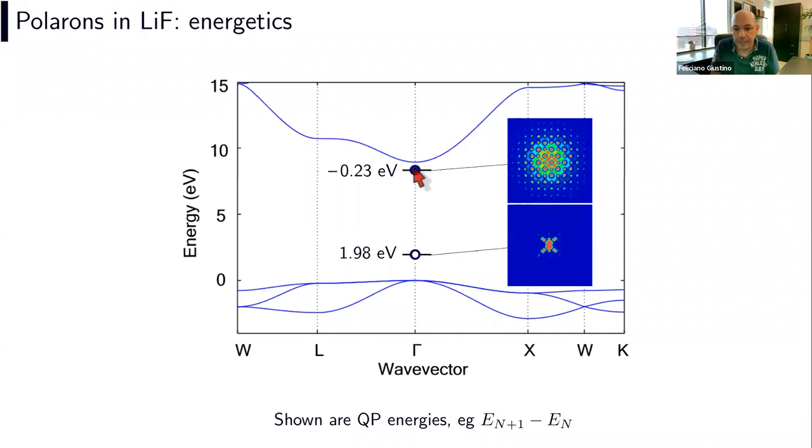And this is reflecting the energetics. If you look, for example, at the energy of formation of the electron polaron, this is about 200 millielectronvolts below the conduction band bottom. And in the case of the hole polaron, it is about 10 times larger, okay? So this also means that there is potentially a significant renormalization of band gaps and the band structures that comes from the localization effects. And I will not have time to show this here, but we performed additional work to understand how this kind of renormalization relates to standard calculations like the Allen-Heine theory, where you look at the change of band structure with temperature. Well, the bottom line is essentially that both effects have to be taken into account. And this effect is particularly significant when you have small polarons and the energy shift is very large.